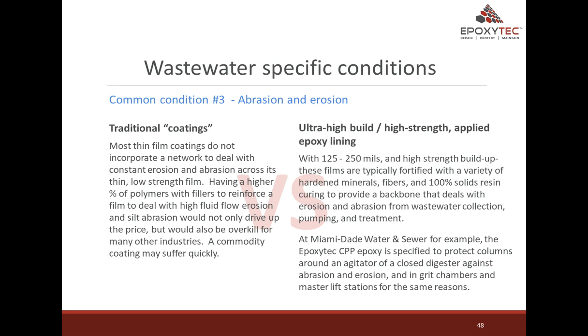Common condition number 3, abrasion and erosion. Traditional coatings. Most thin film coatings do not incorporate a network to deal with constant erosion and abrasion across its thin, low-strength film. Having a higher percent of polymers with fillers to reinforce a film to deal with high fluid flow erosion and silt abrasion would not only drive up the price, but would also be overkill for many other industries. A commodity coating may suffer quickly.